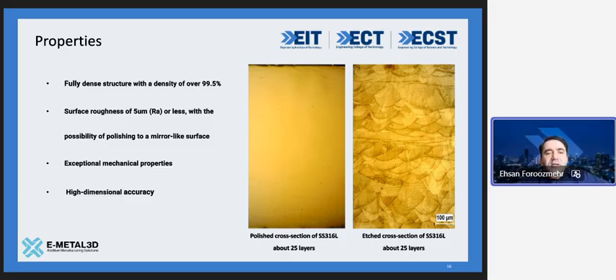The density is over 99.5%, and in many cases over 99.9%, which, if you know, casting, for example, has a much higher percentage of porosity. 2-3% is very common in casting. So when you talk about 99.5 and plus percentage of density, it is considered to be fully dense. Because it is fully dense, it can be actually polished to a mirror surface, something that you can't really expect from, for example, powder metallurgy technology, because that is not fully dense, so you can't actually get to a very shiny surface, but here you can.